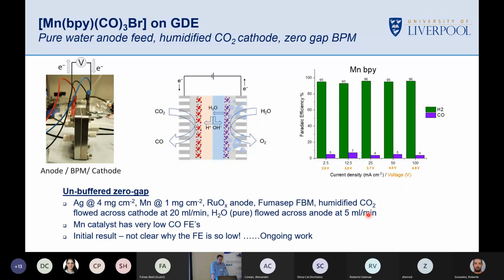And I'm going to be honest here, this is a pure water feed. This is quite a cool cell. So we're literally just feeding water and humidified CO2, no other salts. The reason we feed water to the anode and use a ruthenium oxide catalyst rather than deliberately going to very high pH at the anode is just that in a bipolar membrane you can get small amounts of cation transport if you put in other salts, and we want to minimize that to really see the intrinsic behavior. So we've worked with pure water. So we get lots of hydrogen, not much CO.